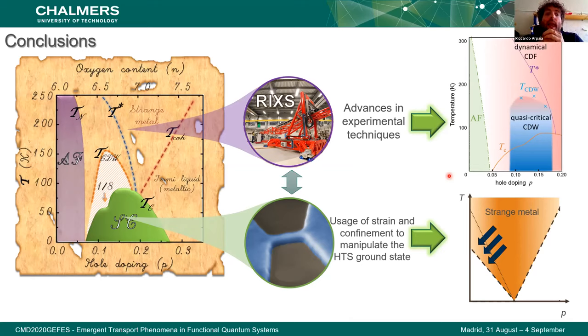And now by combining RIXS with transport and using strain as an additional degree of freedom, we have seen that the charge density wave strongly dominates the transport in the underdoped region, modifying the strange metal behavior that would let the resistance be linear in the whole temperature dependence down to zero. And with this, I just thank you for the attention.